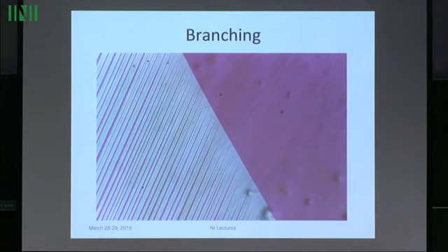What you would expect to see is one of these interfaces move in. But now if you think about it, there's an energy penalty in this more realistic set of models. There's an energy penalty to having these interfaces move in, because there's the interfacial energy on these bands. Because it's not infinitely fine, there's interfacial energy on these bands, and there's bulk energy, either delocalized or localized, in this transition layer.